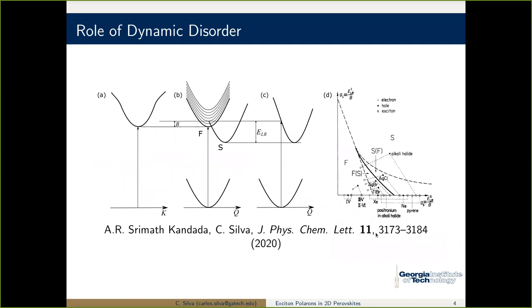This is from that perspective article that I just mentioned. Of course, this figure is not our figure from the article, but it's a figure that we cite in the article. If you look at a range of systems, let's look at this phase-like diagram on the right, where you've got two essentially Huang-Rhys parameters. The Huang-Rhys parameter quantifies electron-phonon coupling, or electron-vibrational coupling. One involves long-range electron-phonon coupling, and another here describes short-range electron-phonon coupling, and we see how these two interplay in systems that are well understood.